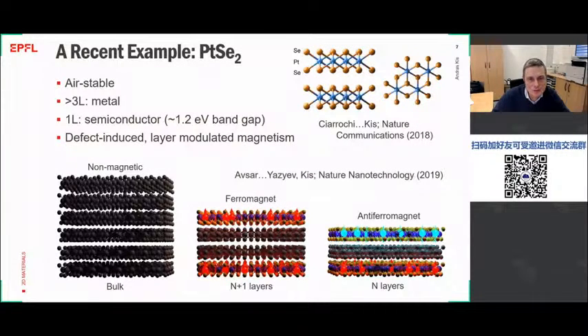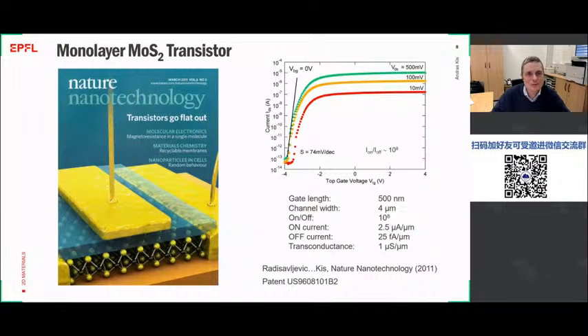What was our main contribution to the field in the beginning was that back in 2010, and this was published in 2011, we showed that we can make a transistor using a single layer of molybdenum disulfide. This was an important contribution because in those days, pretty much all the research on 2D materials was focused on graphene and making devices with graphene. Now, the problem with graphene is that even though it has a lot of interesting physical properties, it doesn't have a band gap.